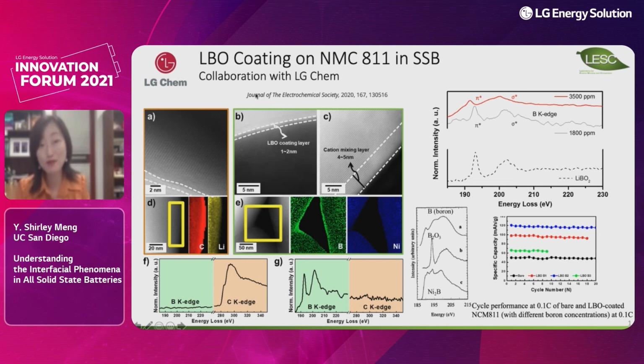The NMC 811 cathode material uses a single step borate-based coating, and this borate was pre-selected by my colleague Professor Shirley Meng's screening process by computation, which showed a very good protective nature for the NMC against the solid electrolyte. Once we establish the right environment for the lithium boron oxide coating, we can stabilize the cathode materials very well. So you see the utilization here is still not perfect, and I will dive into the details of why at that time we could not utilize all the capacity of the NMC 811 cathode materials.